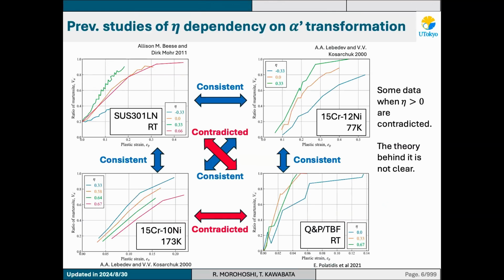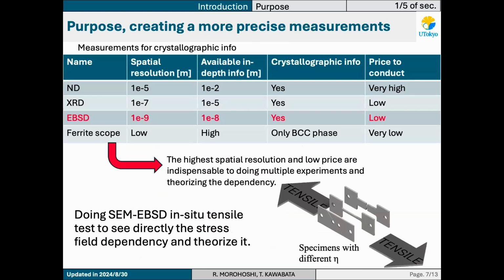For example, there are 4 major previous studies investigating the stress field dependency of the martensitic transformation. Especially in the data around high stress triaxiality, they contradict each other. So we need to choose the most precise way to measure the stress field dependency of the martensitic transformation. Finally, we chose the in situ SEM EBSD tensile test as the best one, because the highest spatial resolution and the low price are indispensable to doing multiple experiments and theorizing the dependency.